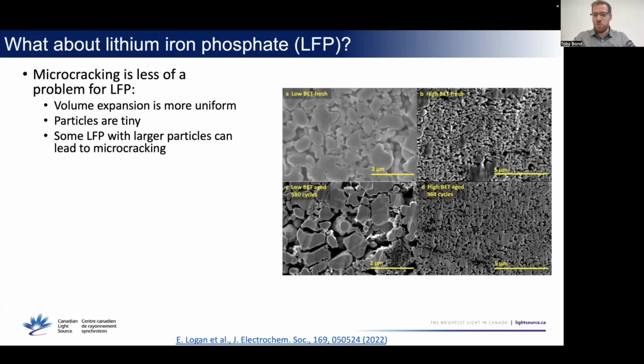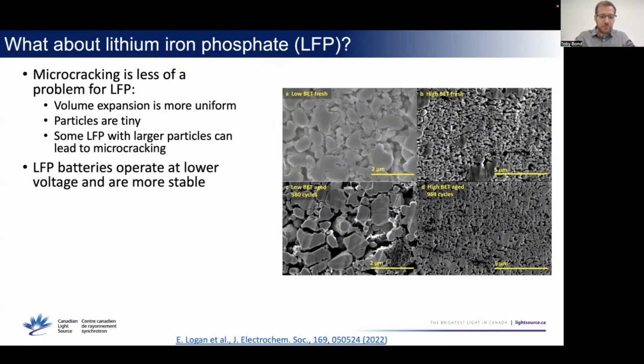And this is a typical material over on the right here, in a fresh cell on the top and then an aged cycled cell on the bottom. And these particles are very, very small. They're tens, hundreds of nanometers in size. So the microcracking isn't as big of a problem when you have really tiny particles. But if you have large particles, then you actually do see this microcracking. So it can be an issue, but it's just not as big of a problem compared to NMC and NCA.